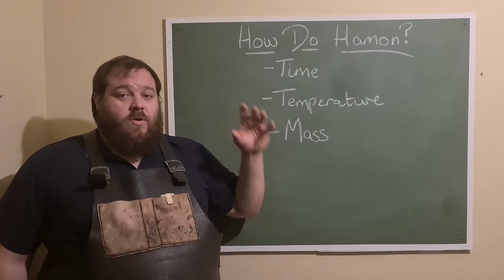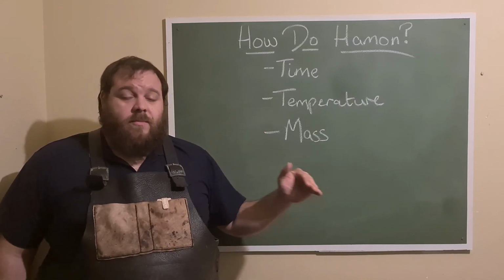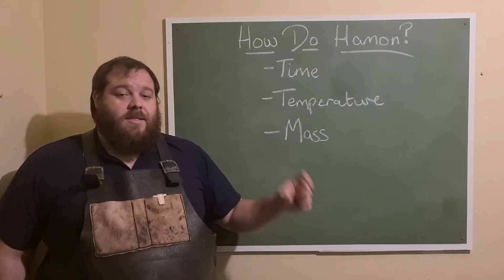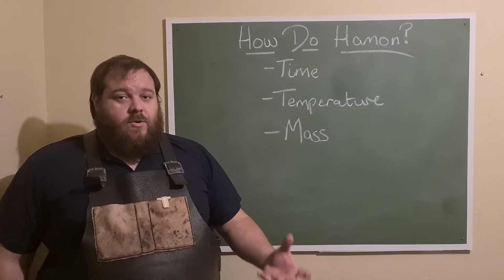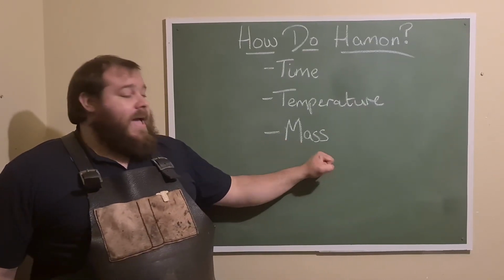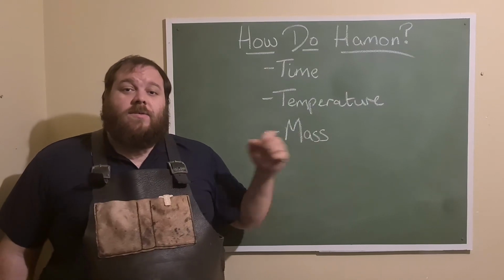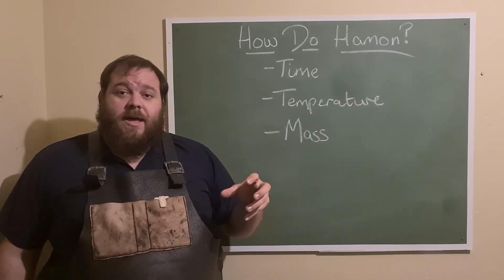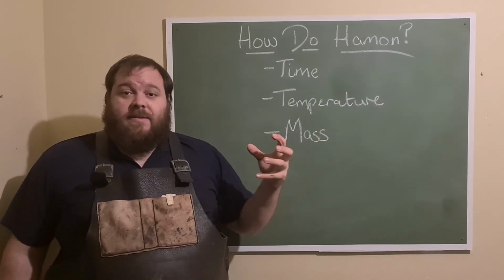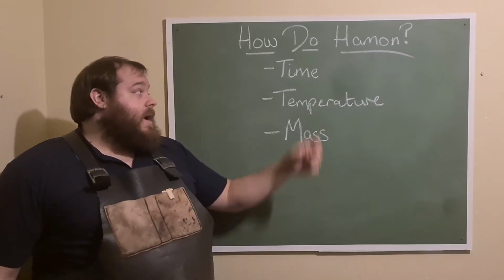Because we're trying to quickly quench the areas that we want to transform into martensite, and we're trying to slow down the points at which the other parts cool. So mass is your biggest ally. So therefore, with a high mass in the spine, you can get a decent Hamon without much worry about time and temperature.